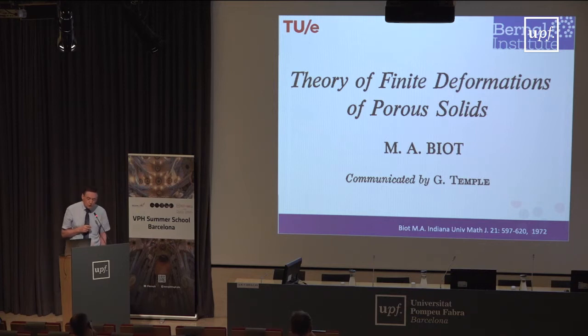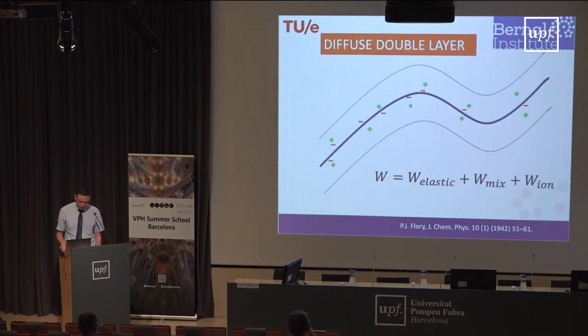So what we use, practically speaking, in order to study these gels and intervertebral disc, is the theory of finite deformation of porous solids. And it's actually a very old theory, because it dates back to 1972. On top of that, we use the insights from Flory, also a Nobel Prize winner, on swelling, who argued that you need three free energies. One is elastic free energy, the second is mixing free energy, and the third is the ionic free energy. Ionic free energy is the one responsible for Donnan osmosis. Many people working in cartilage and disc know they work with Donnan osmosis. So this free energy of ions is very, very important.